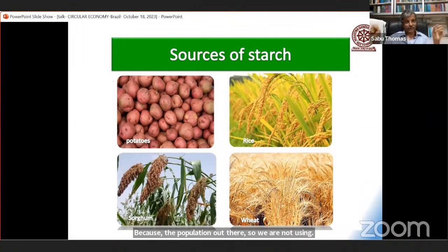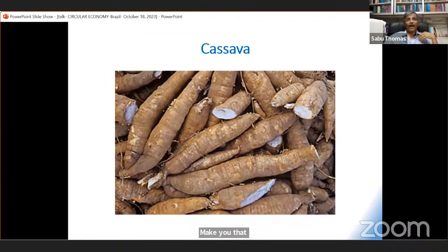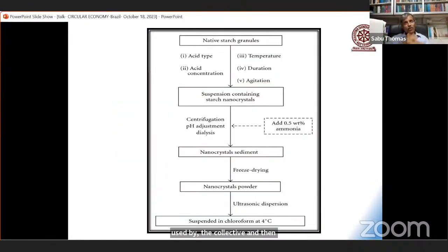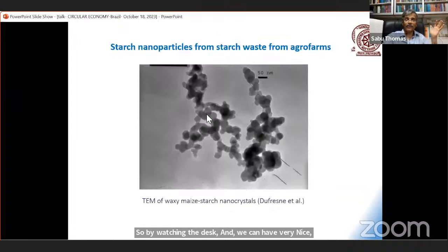So what we do is we collect the waste material in agricultural lands, like potato, rice, wheat, sorghum, tapioca. We have plenty in Kerala. So during the harvest time, my PhD students go to the harvest ground, the field, and collect all the waste from it that cannot be used by human beings and animals. We collect it, and then we do a washing with acid. By washing with acid, we remove all the phosphorus part. And dear students, we can have very nice nanocrystalline powder of starch. You can see some electron microscopic pictures of nanocrystalline starch.